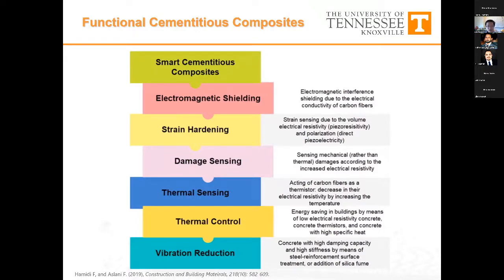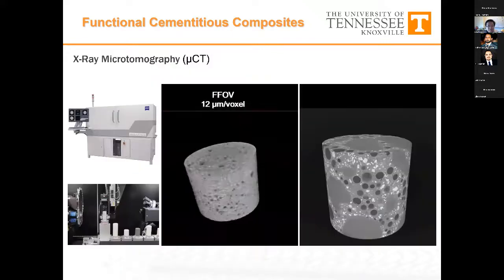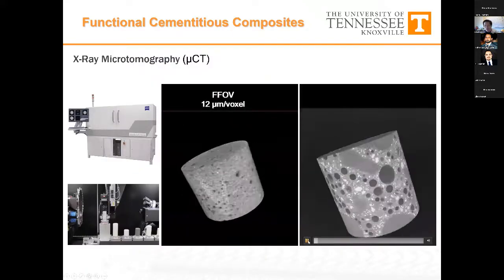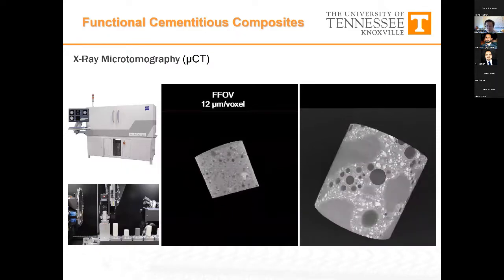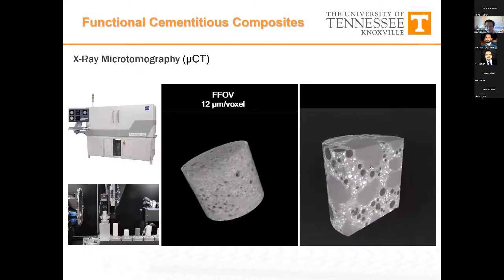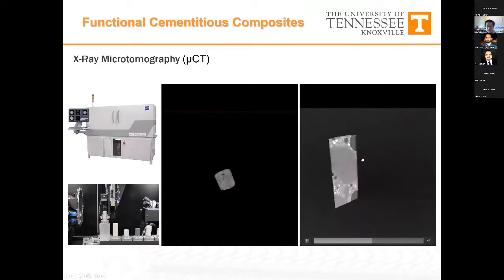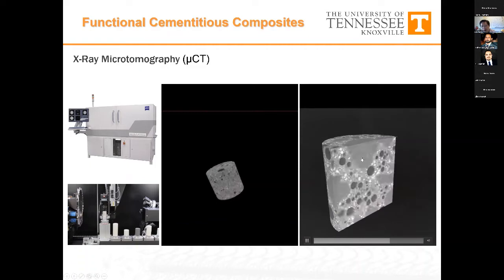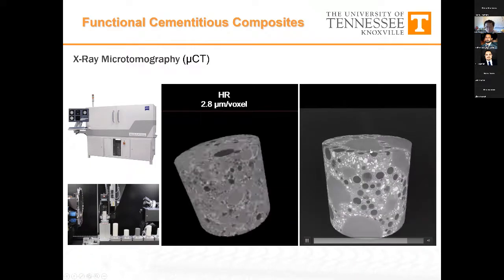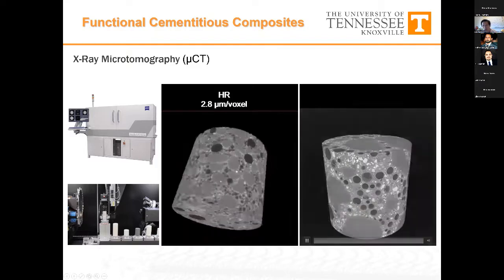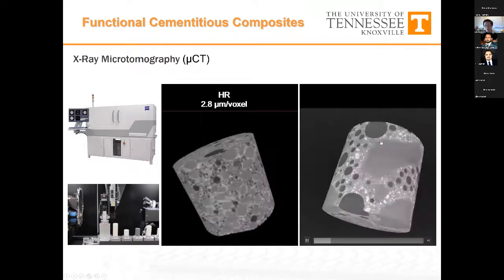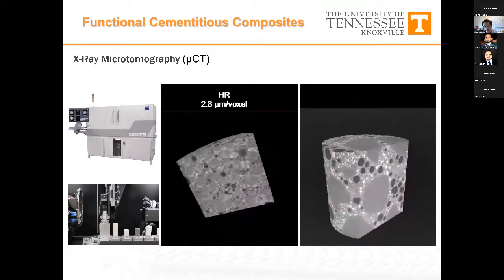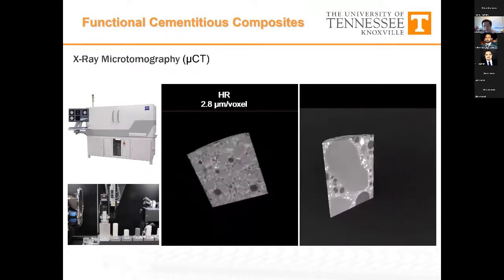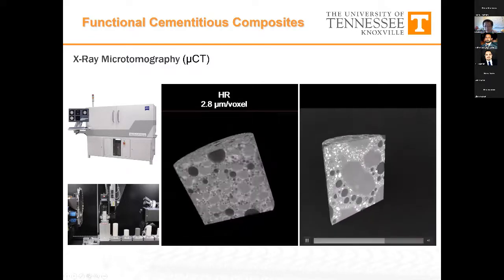And sometimes we can achieve mechanical functionalities by invoking internal damping, as an example, in the material system. So if we look at a cementitious composite system, right, its microstructure, these are the three different phases that we have talked about previously, with a continuous matrix that's a hydration product of the binder system, the aggregates, and also we can add in functional additives. In this particular case, it's a core-shell particle or particulate matter that we added to the mix, shown in its microstructure.